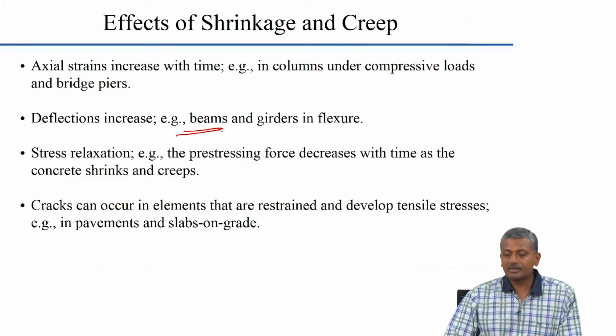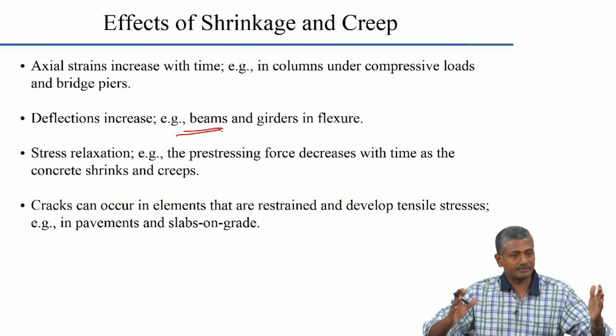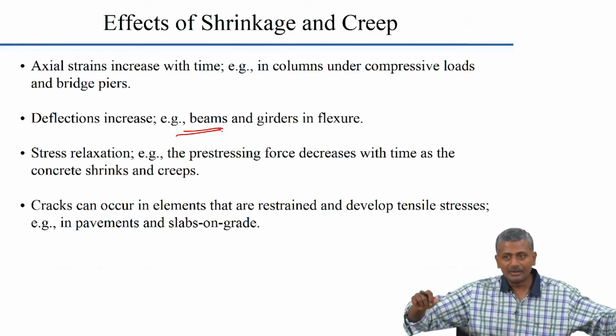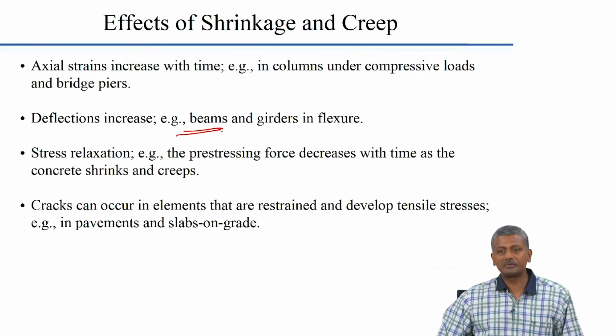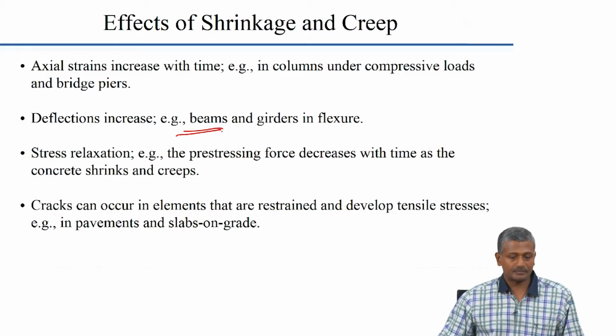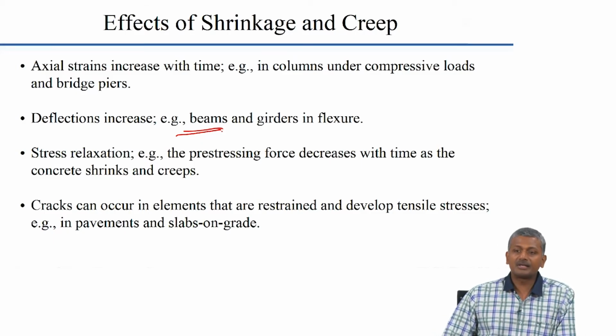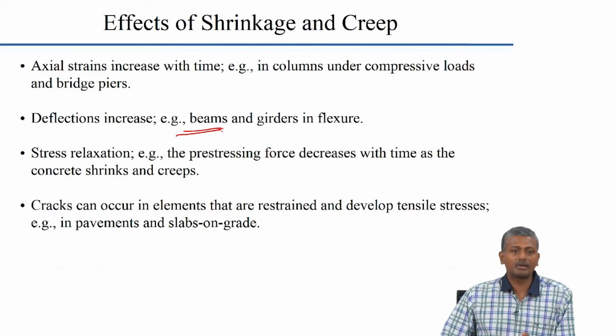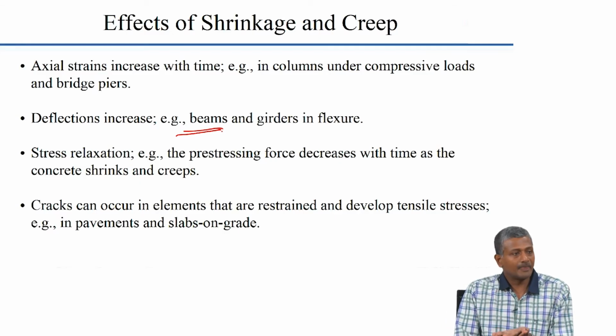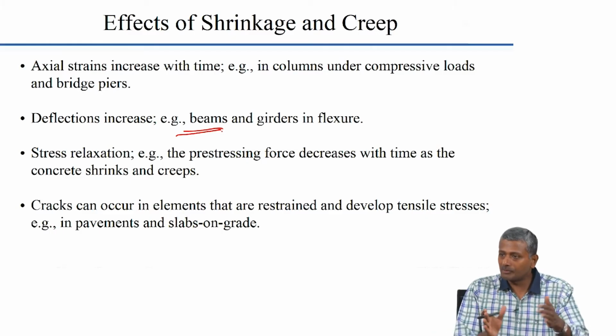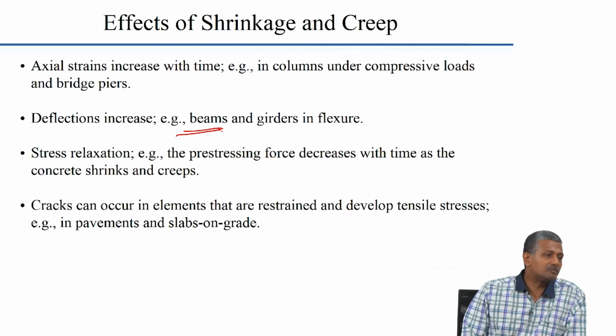Stress relaxation can happen in the case of pre-stressing steel. So, pre-stressing force decreases with time. As the concrete shrinks and creeps, concrete goes in. So, the extent of pre-stress that is transferred by the steel keeps getting reduced with time. And cracks can occur in elements that are restrained because of the movement of the concrete in response to the volumetric deformation. Especially when you have a pavement, for instance, which is sitting on soil, the restraint offered by the soil to the volumetric movement of the pavement can result in cracking in the pavement.